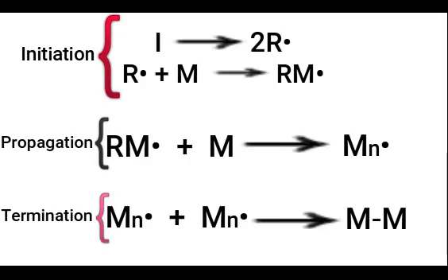So, as viscosity increases, the ability for these growing chain radicals to diffuse decreases, and so the rate of termination decreases. This means, assuming that there are abundant initiator molecules and monomers present, that the concentration of the growing radical chains will gradually increase. This means that more propagation reactions will occur, resulting in an increased rate. These propagation reactions are exothermic, meaning that more heat will also be released.